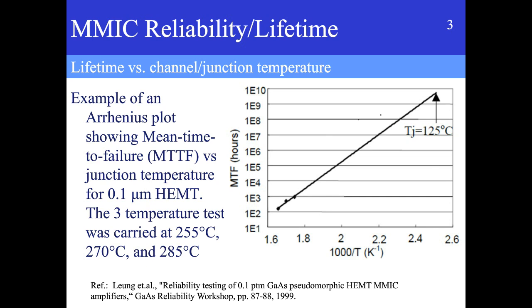And so, for example, 125 degrees C is shown on the right, and then what's shown on the left, these three points are the temperatures 285, 255, and 270. The important point to take from this graph is that the lifetime depends exponentially on the temperature. And so if your transistor crosses the critical temperature, then its lifetime is going to change very, very rapidly.